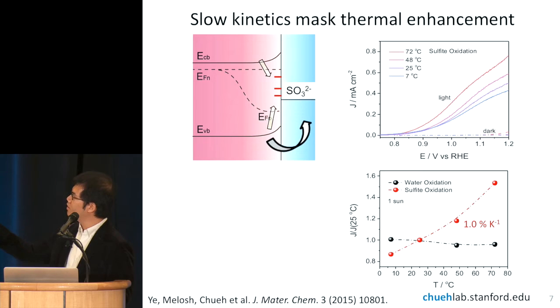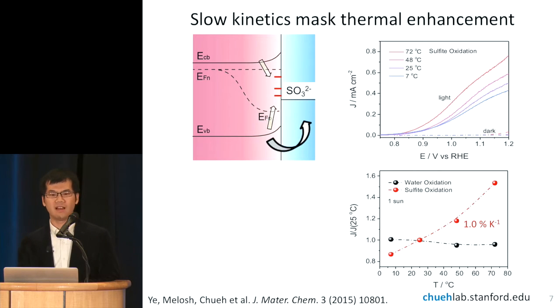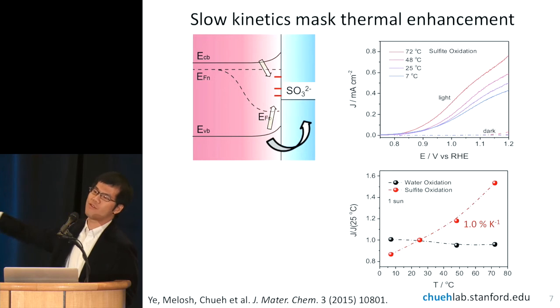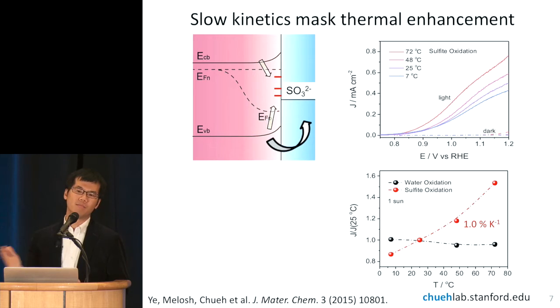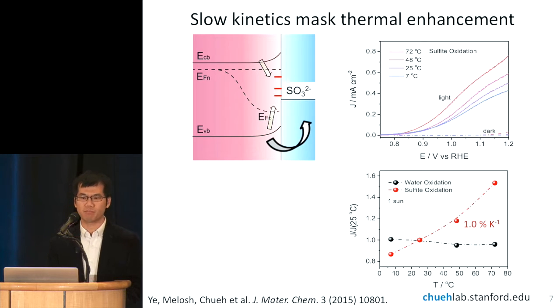And on the plot on the bottom, I'm showing you how much the current is enhanced over room temperature. Without the sulfite fast redox couple to scavenge the holes that are being generated, you have a very, very flat line. That's what's in black. But when you put in sulfite, the curve goes up quite a bit, and the coefficient we're getting is about 1% per Kelvin. So every degree you turn up, the photocurrent increases by 1%.